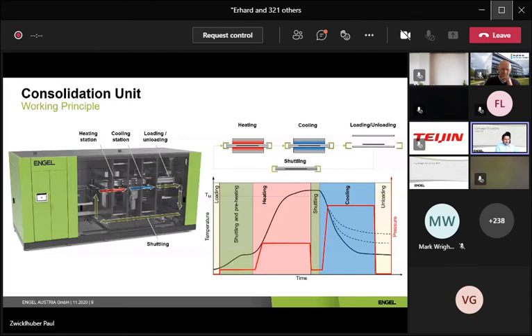During the cooling process, the energy balance of the process can be increased significantly. The warmer the stack can be removed, the better the energy balance, because of the remaining heat in the molds, and this heat can heat up the stack during the transport. You can see this shown here.